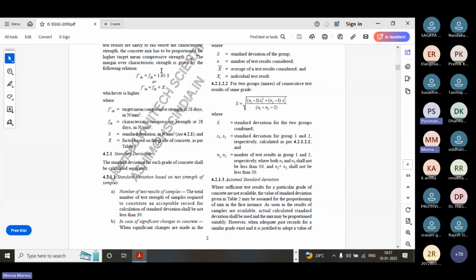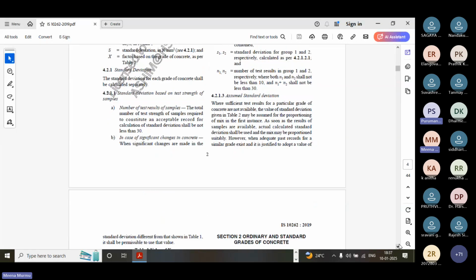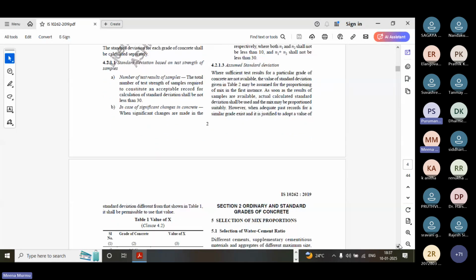This is given in the 1982 code. Why are we taking only 1.65? As per the definition, characteristic strength means that if we take 100 samples, 95% will pass, so 5% of results will fail. According to that, the 1.65 value came. After that, we finalize the target strength, and according to the target strength we finalize the water cement ratio.